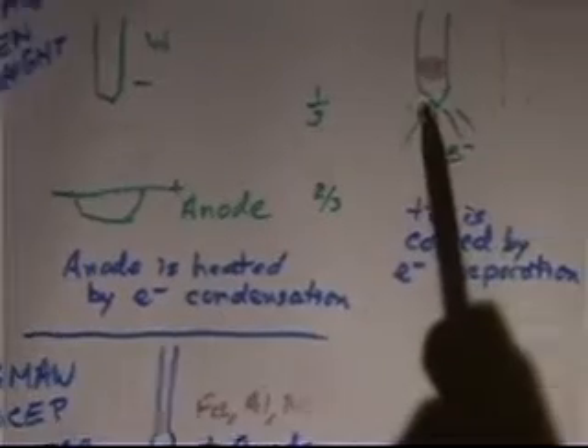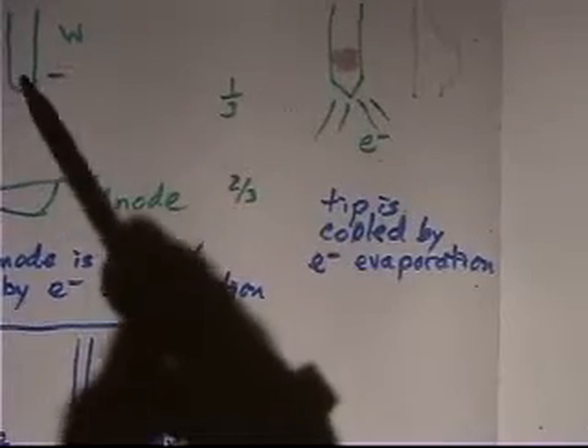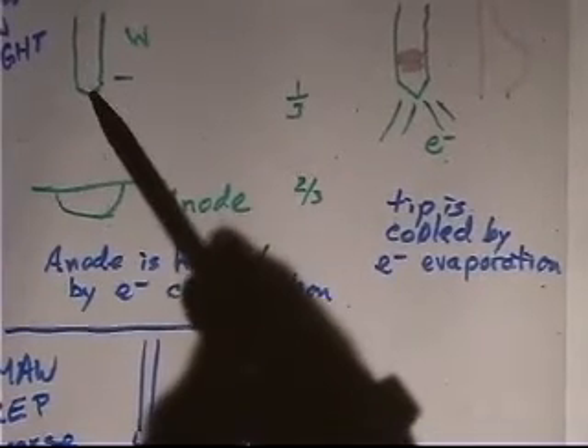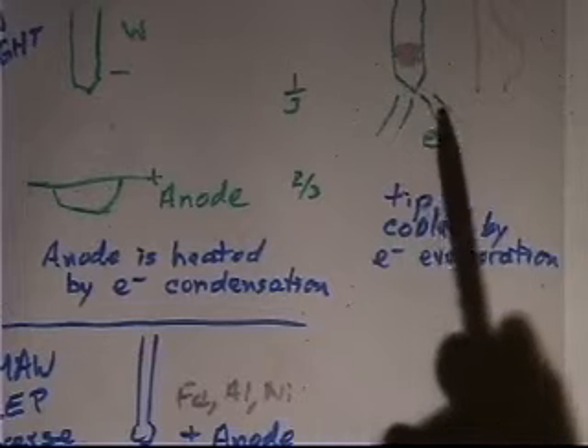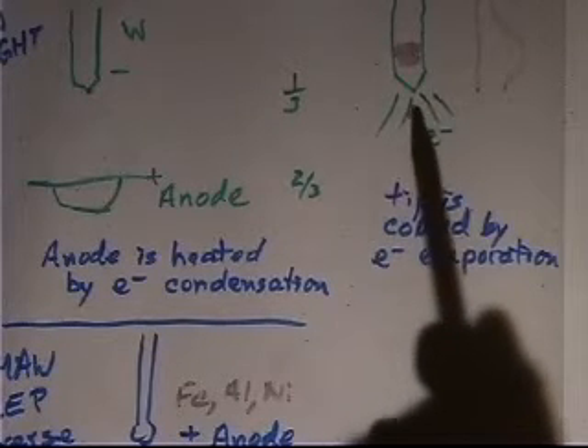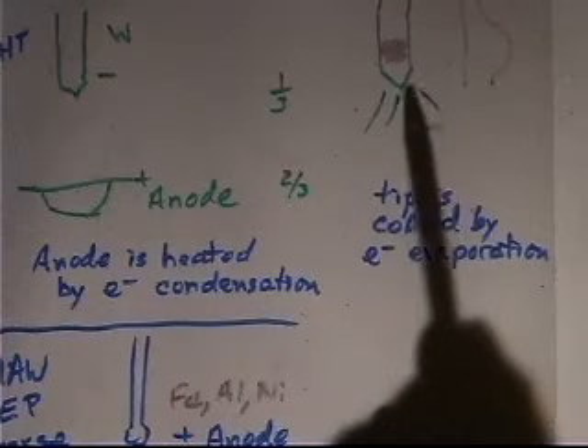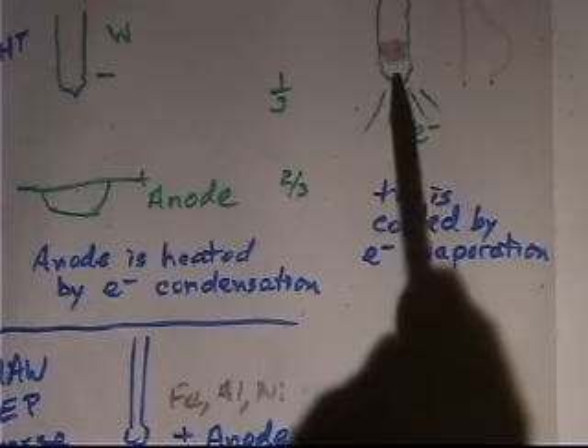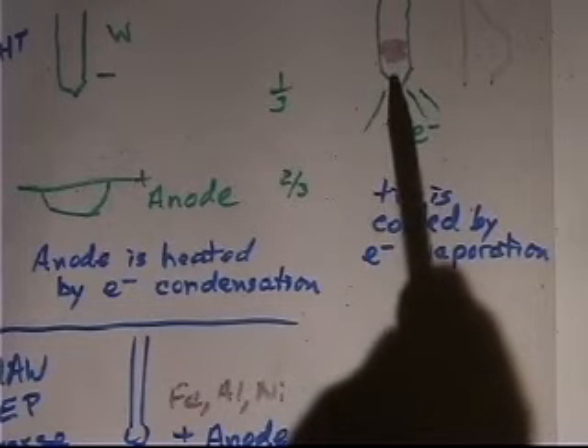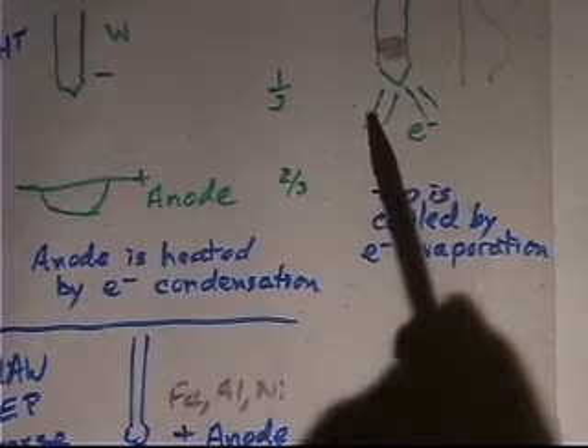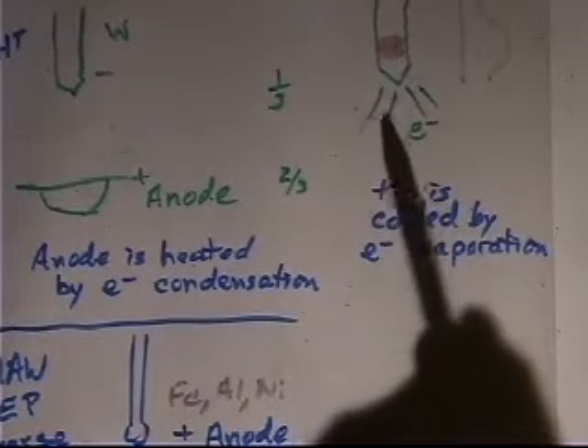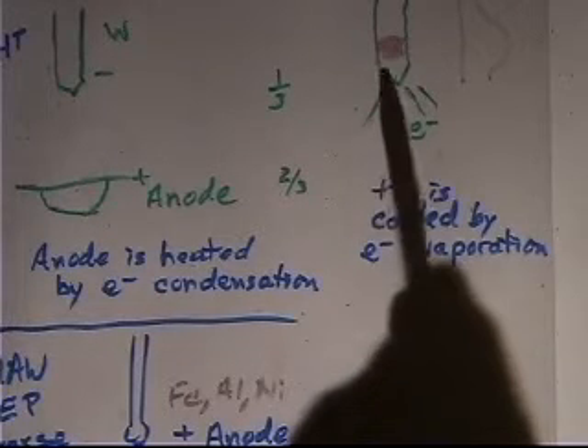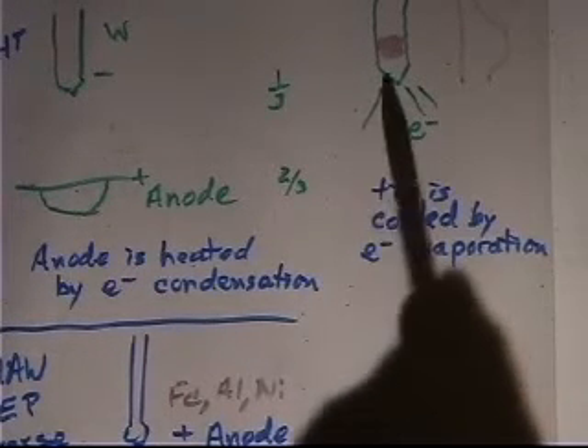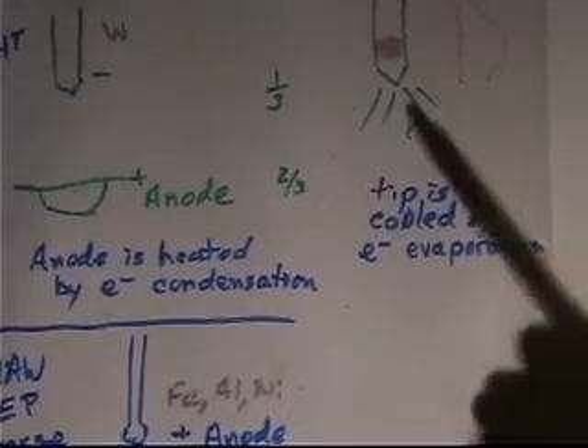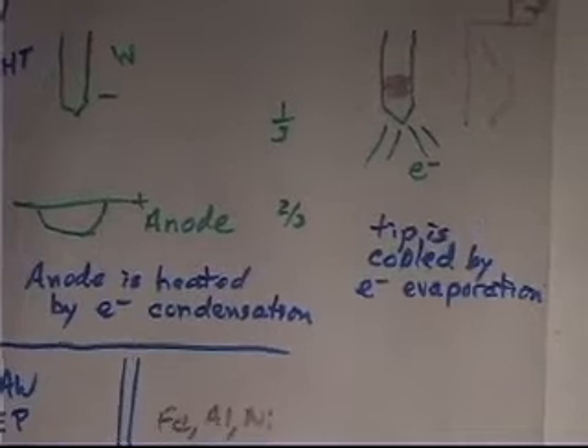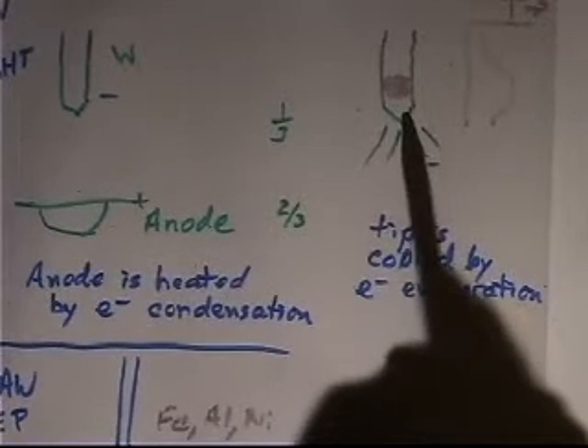Now, if I go over here and look at the electrons coming out, I actually will find that the electrons coming out of the cathode will cool the tip of the cathode, because the electrons are essentially being vaporized from the surface. Sometimes they call it in the literature the heat of vaporization. You have to put in the work function voltage to get them out of there. By taking the electrons from a low energy state and putting them in a high energy state, that's the same thing as evaporating electrons from the surface. They're carrying the heat of vaporization as they go from the solid phase into the gaseous phase. That's one way to think about it. That means they actually cool the electrode. And in fact, Professor Savage at RPI once took an optical pyrometer and measured the temperature.